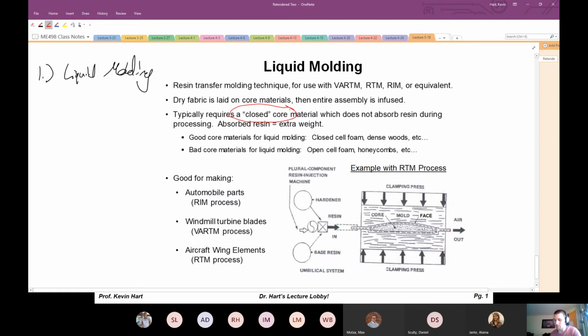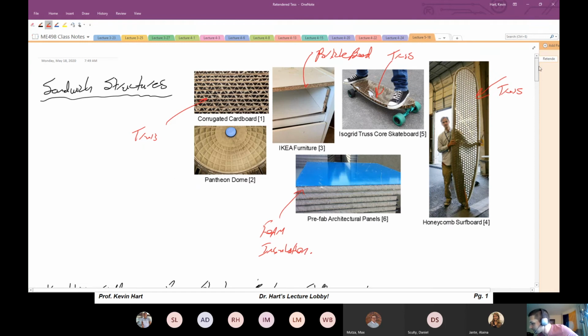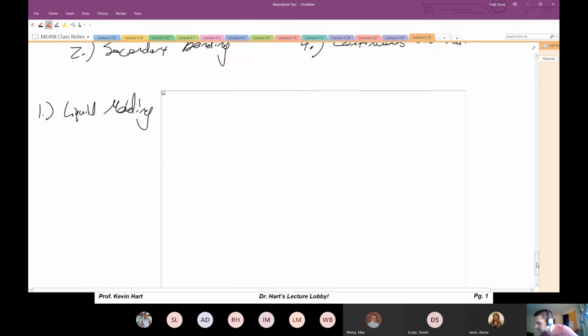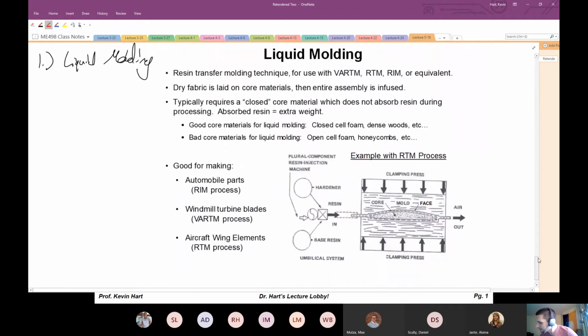So like a closed cell foam or a very dense wood that does not allow liquid to penetrate into the core if it comes in contact with it, right? So closed core is required in this particular situation. All right. Absorbed resin, extra weight, always bad in composite manufacturing. So good cores for liquid molding might be closed cell foam, dense woods, etc. Bad core materials for molding: open cell foams, honeycombs.